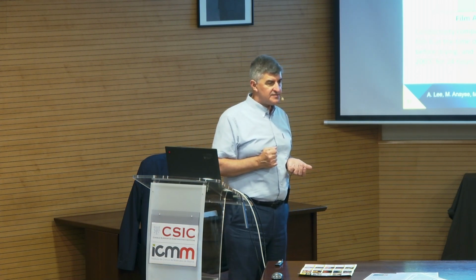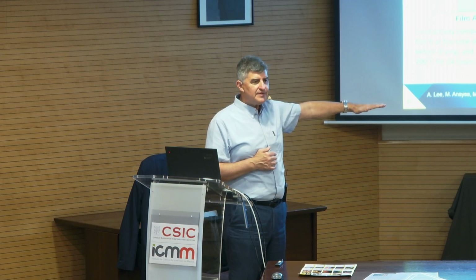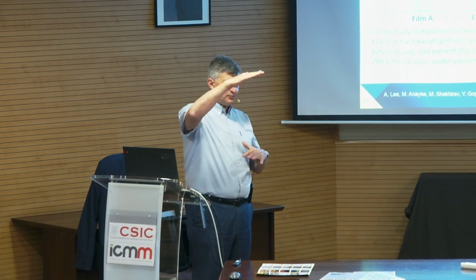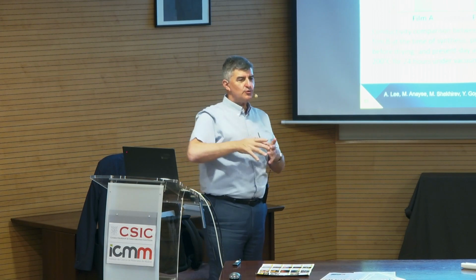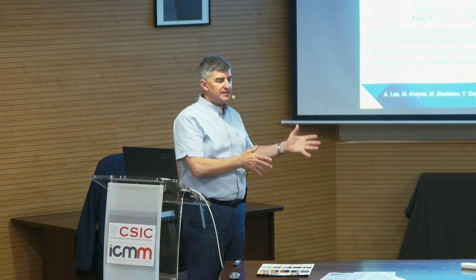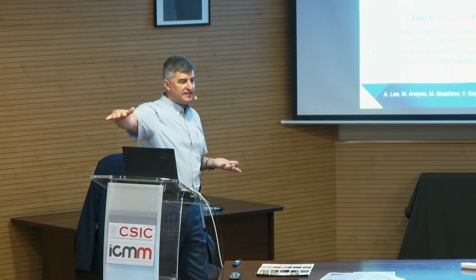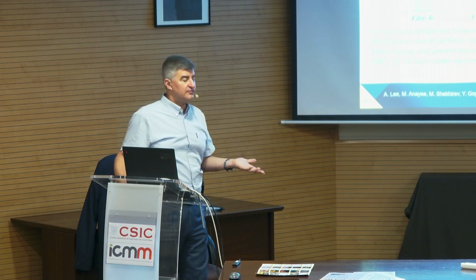And let me just take you back 15 years, 20 years. Wafer scale graphene, or continuous sheets of graphene on copper, did not appear overnight. There were millions, probably tens of millions, if not hundreds of millions of dollars of investment. People started with taking silicon carbide crystals, heating up at 1600 C, transforming monolayers into graphite, peeling off single graphenes to have larger crystals. After that, growing on nickel, and then the copper method appeared. Similarly with boron nitride and molybdenum sulfide, covering the entire wafer. All this work is still to be done for MXene.